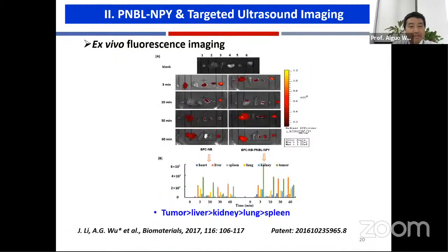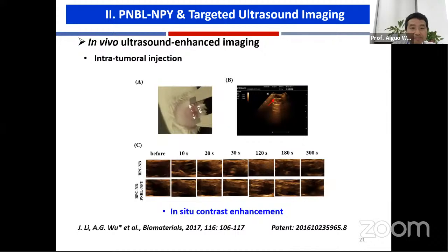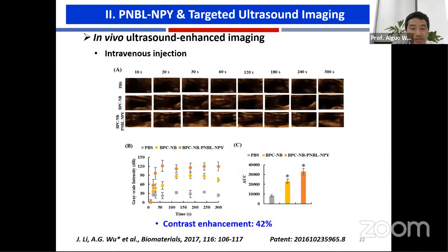And we found in ex vivo fluorescence imaging that the signal in the tumor area is better than in the liver, kidney, lung, and spleen. And it means most of the nanobubbles go to the tumor area. And for the intratumoral injection, we found very high contrast enhancement. And we found contrast enhancement of over 40%, 42%, with intravenous injection for the in vivo ultrasound imaging.